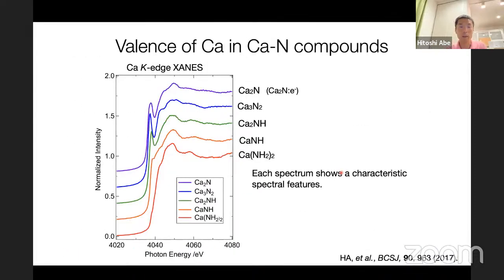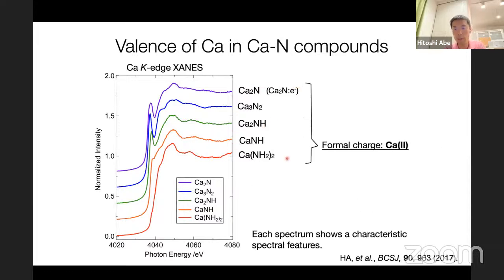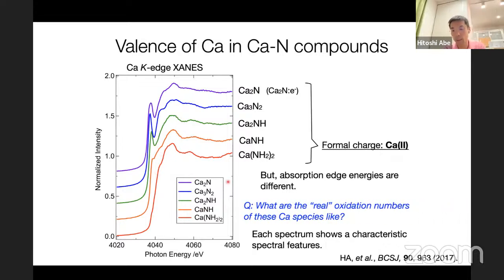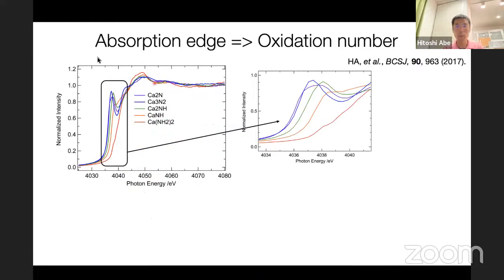Okay, here are the calcium K-edge XANES spectra of the calcium and nitrogen containing compounds. Here, all these chemicals have the formal charge of calcium 2+, but absorption edge energies are different. So the question is, what are the real oxidation numbers of these calcium species? Each spectrum shows characteristic spectral features. And here we can estimate the oxidation numbers by analyzing the absorption edge position.